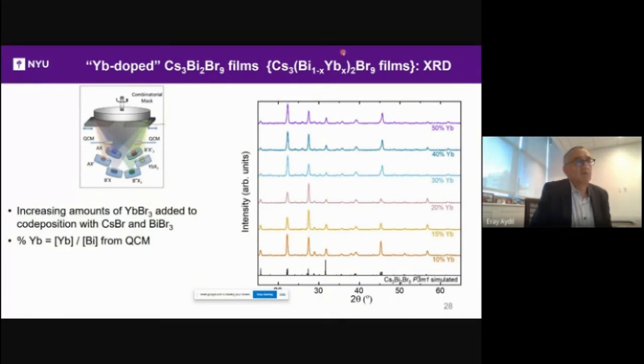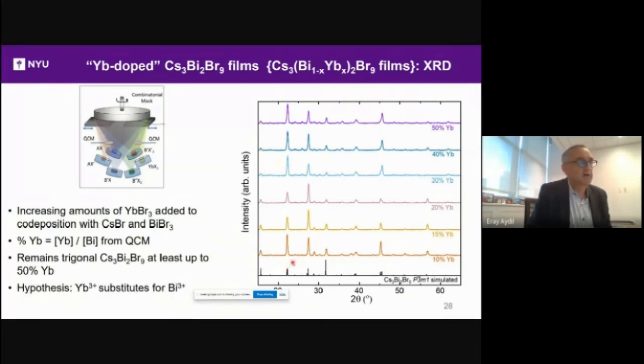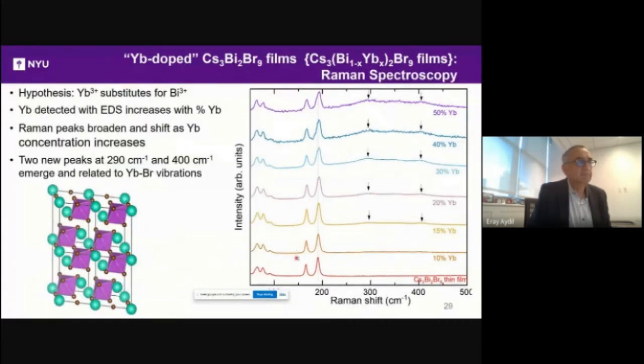So we started with the hypothesis that ytterbium substitutes for the bismuth. And we put in up to 50%, so about half of the bismuth substituted with ytterbium, or enough ytterbium in there to substitute half. And you can see that the X-ray diffraction doesn't change very much. It remains trigonal, at least up to 50%. And so our hypothesis is that ytterbium 3+ substitutes for bismuth 3+.